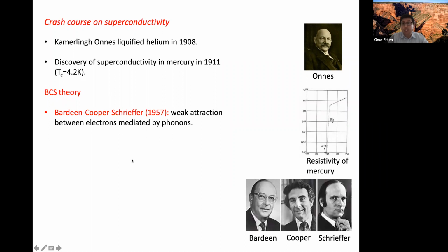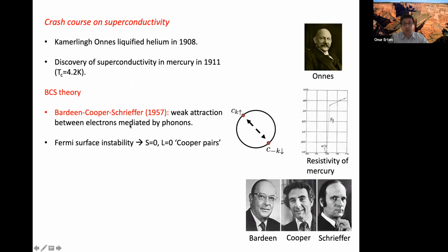They showed that the weak interaction between the electrons mediated by phonons gives rise to a Fermi surface instability. Instability meaning that this will happen regardless of how small the interaction is. As long as you have some effective weak interaction between your electrons on the Fermi surface, you will always have a superconductor, as long as there's no other broken symmetry.